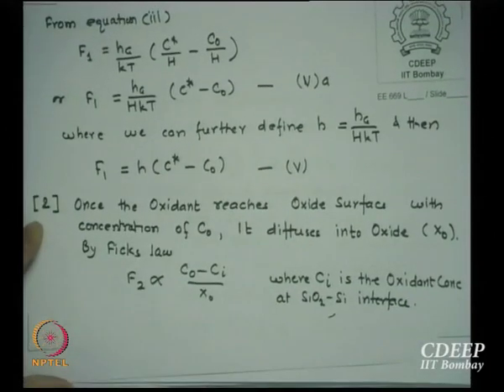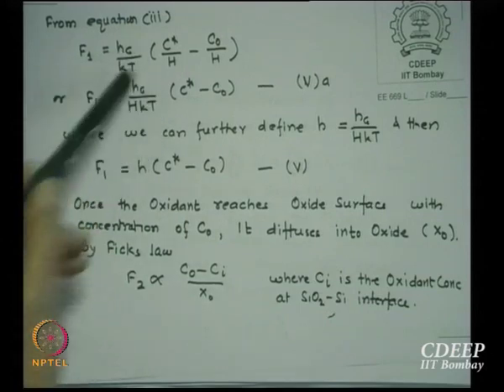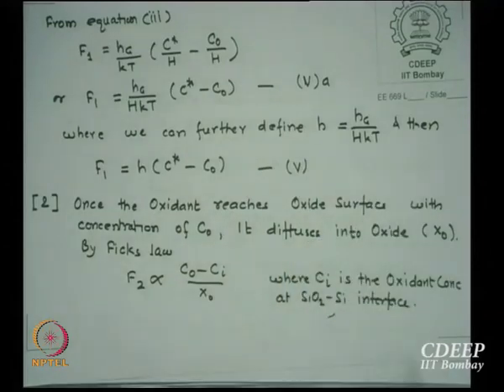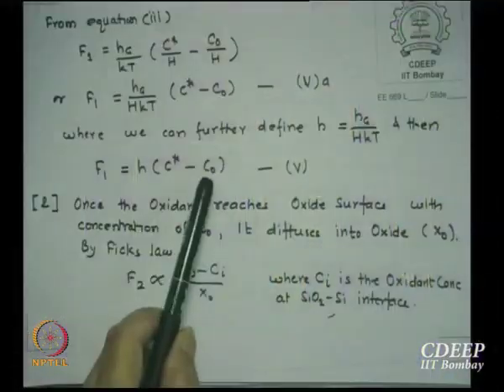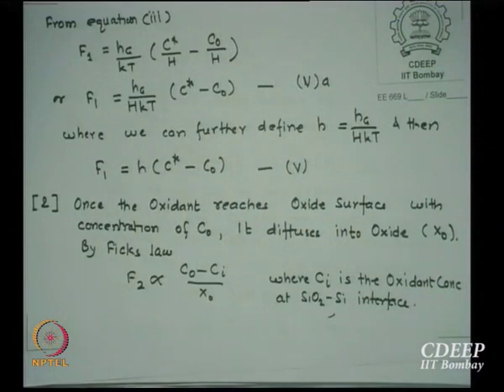So if I do that, F1 is Hg by Kt C star by H minus C0 by H, or F1 is Hg by capital H Kt times (C star minus C0), and I can redefine this Hg upon HKT, which is all constant at a temperature, mass total flow and pressure. Then Hg upon HKT is redefined as term H, which of course is proportional to mass flow. So F1 is H times (C star minus C0). So first flux in the gas phase is related to solid phase concentration difference, H times (C star minus C0). So this is the first flux we obtained.